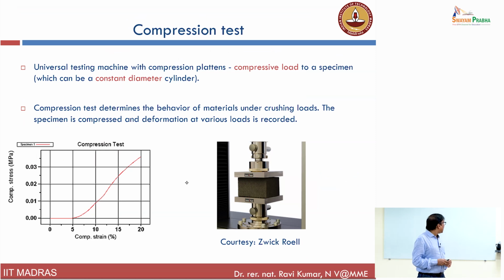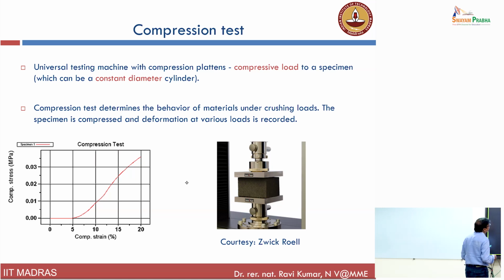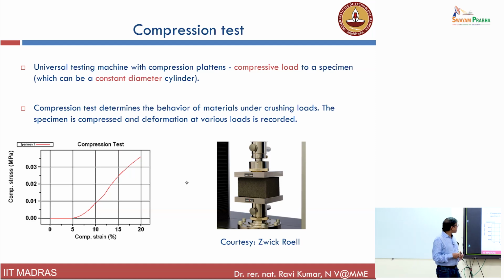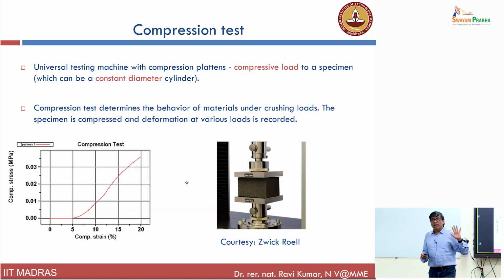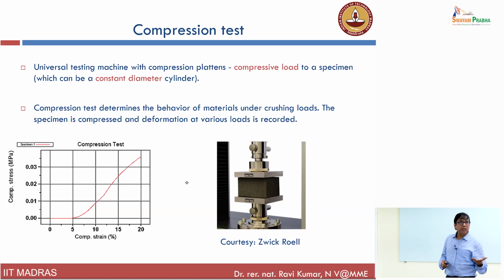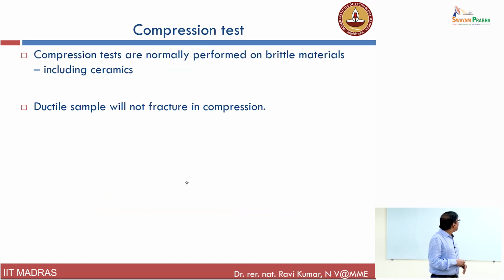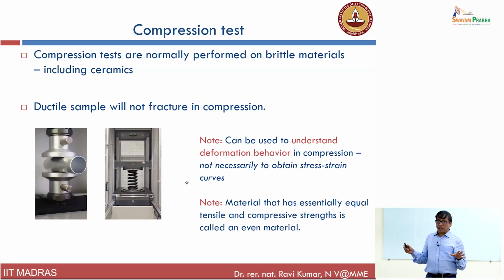for ceramic samples. It's not so easy, because ceramic samples are not so easy to manufacture in a certain way. So generally, there is more leeway on the shape and size of the samples. But to test the strength and get a typical deformation response for ceramic materials, we always use compression tests. We use typically the same strain rate, in the order of around 10 power minus 4 per second, and generate the load displacement curve. And for that matter, you can do that for all brittle materials.